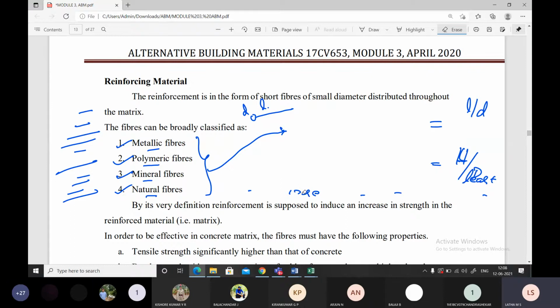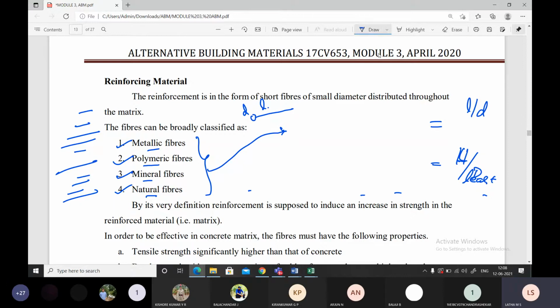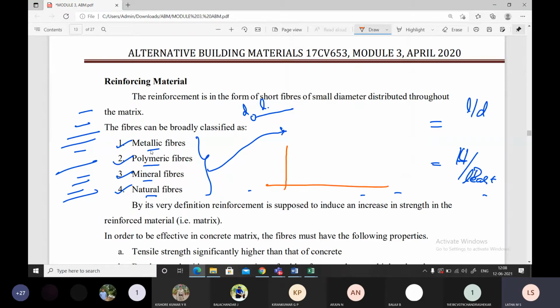For an aspect ratio, now I'll take in particular. I'm doing some research in the laboratory, and you'll use metallic fibers for different aspect ratios. Let me say, after your calculation of aspect ratio, you get values of 0.2, 0.25, 0.3, 0.35, and so on. You'll get metallic fibers of these aspect ratios from the market. Then using your concrete cube testing, you're done, no students, in the laboratory. 150 by 150 by 150. Cube testing. Yes, ma'am. So you will start getting the graph now.